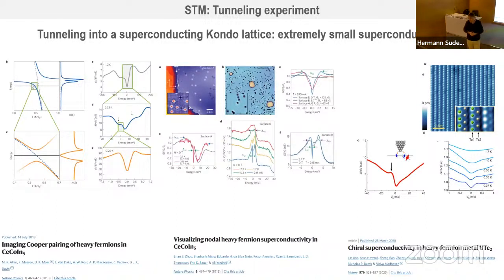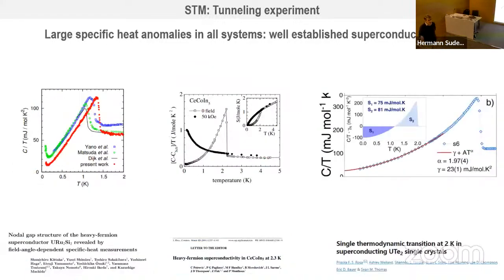Now there is one story which has been very puzzling for an experimentalist. And it is that when you measure with tunneling spectroscopy, you always see these kind of faint features. Here, for example, this is in cerium cobalt indium 5, and this one, which is another F electron-based superconductor, and this is on uranium tellurium 2, which is this nice chiral superconductor, where you have these kind of small features here, which is, okay, why not? But it's not something easy to explain, particularly when you look at the specific heat. So the specific heat really tells you if the system goes superconducting because it tells you how many excitations the bulk has. And what the specific heat tells you is that at zero temperature, there are zero excitations. So the gap is fully open.